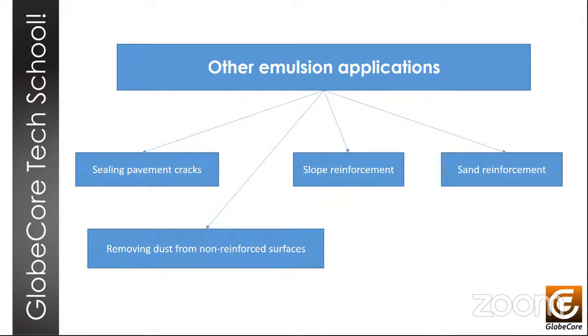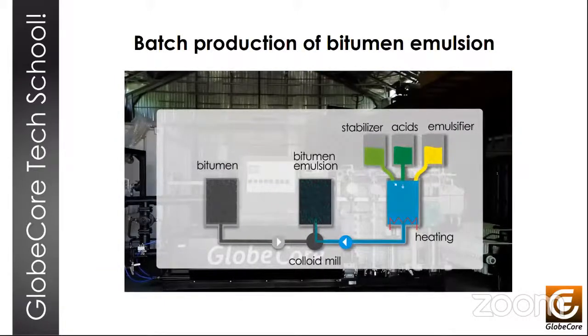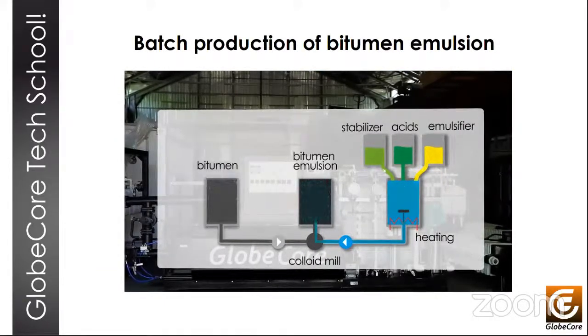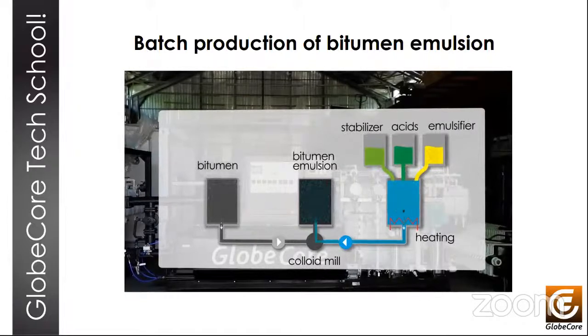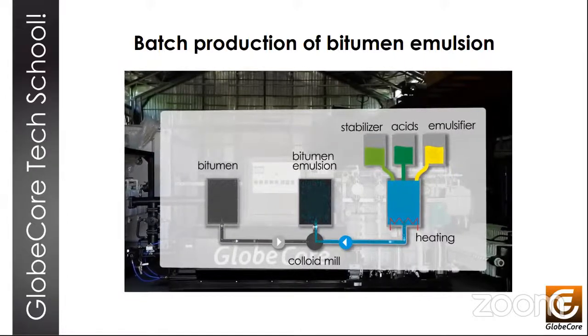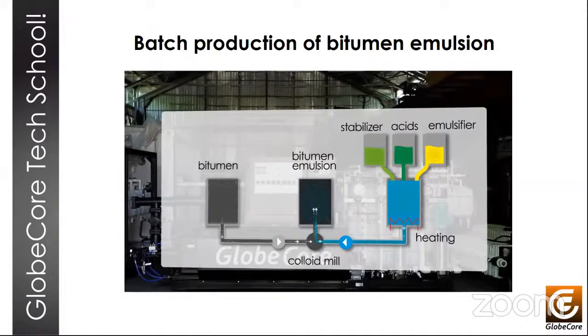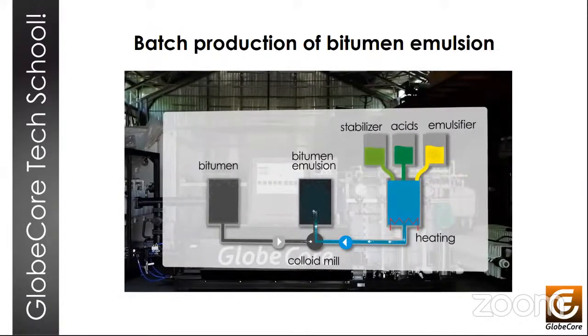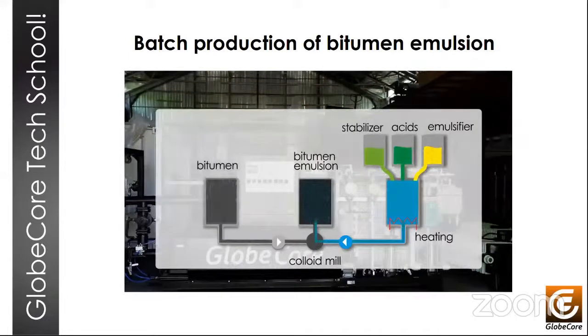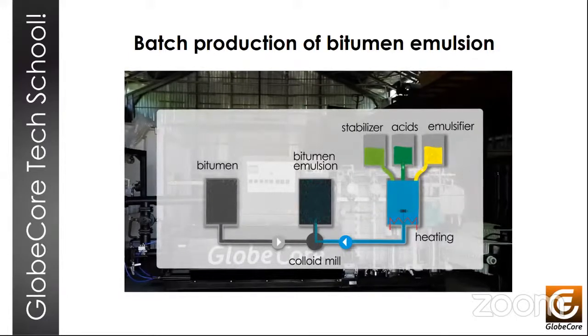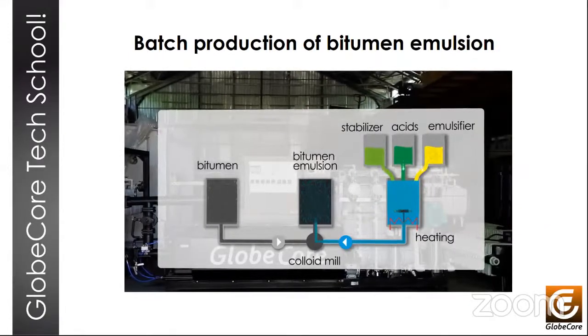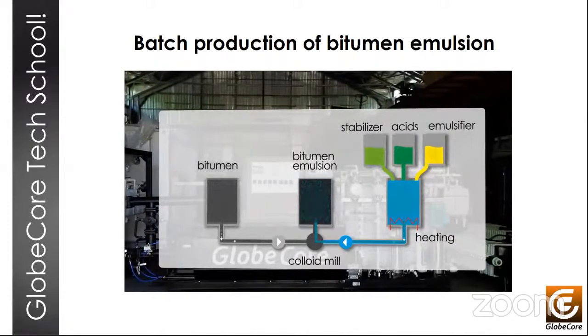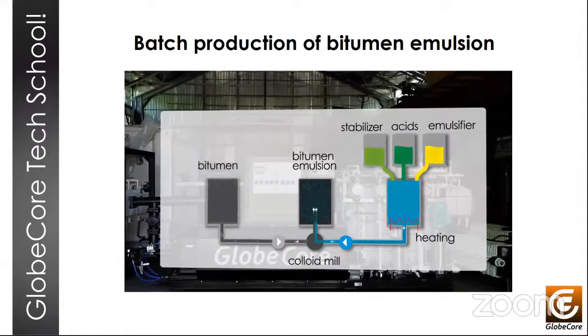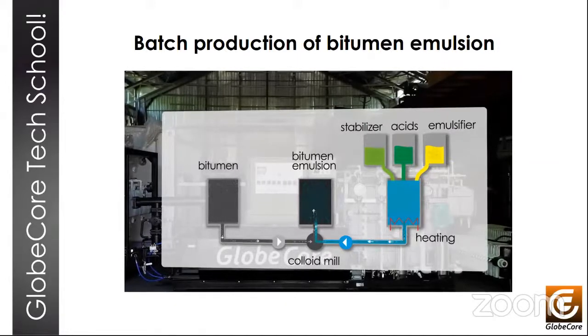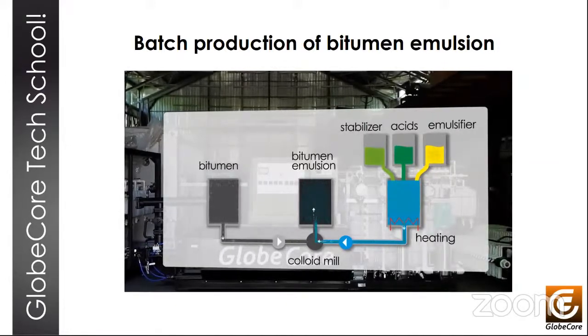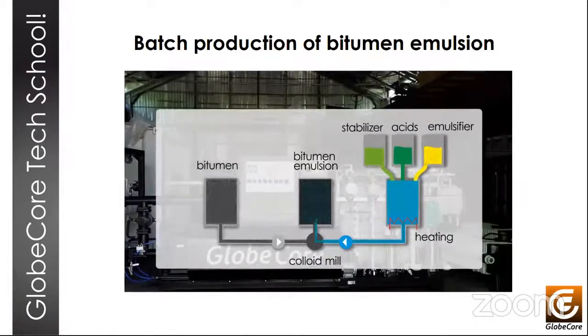Right, so bituminous emulsions are usually made using a colloid mill, but they can also be prepared using other dispersing devices. In a colloid mill, an emulsion is produced by passing a mixture of hot bitumen and a water phase between a rotating rotor, basically a disc or cone, and a non-rotating stator. The rotor, just like the stator, can have slots or teeth to create a turbulent flow of the material.